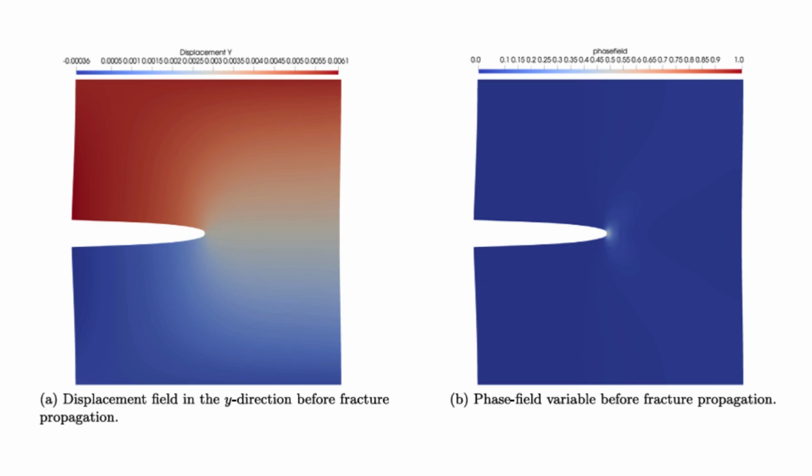What did they find? They found it mattered a lot, especially right when the crack starts to really go. That onset of fracture is super fast. A sudden event. Exactly. If you chose too large a time step, delta t, the simulation would just sort of skip over the true peak load. It would underestimate how strong the plate actually was right before failure. So you needed tiny time steps to accurately capture that critical moment. Yes. Smaller steps gave a much more accurate picture of that peak force.